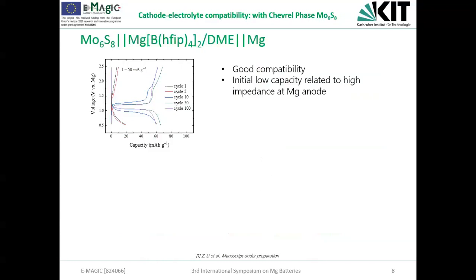But the case is that we tried it, and the compatibility between our borate electrolyte and the Chevrel phase is quite good. As shown in the charge and discharge curve here, we have a nice plateau and also a good capacity and low overpotentials after the first few cycles. The initial low capacity is related to the activation process at the magnesium side. So we also observed a similar activation process in the magnesium symmetric cell using this borate electrolyte.